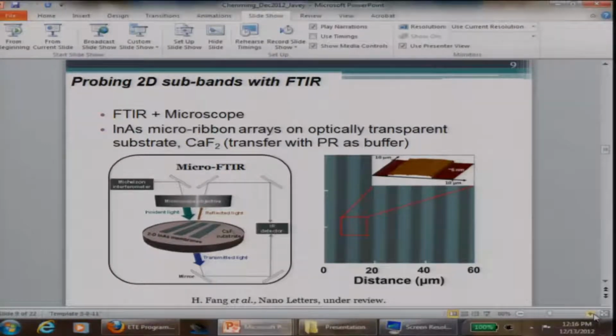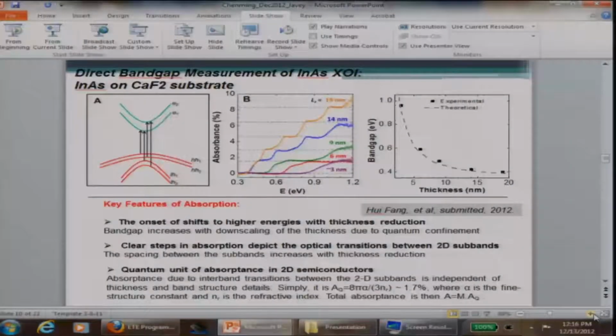The nice thing about the layer transfer process is that you can grab your material, in this case indium arsenide, and transfer it onto any substrate. You don't have to transfer them necessarily to silicon dioxide. In this case, in fact, we transfer them to an optically transparent substrate like calcium fluoride. So now you have indium arsenide on an optically transparent substrate. You can do absorption very easily. You can do absorption studies. And from that, you can look at your band structure directly, experimentally.